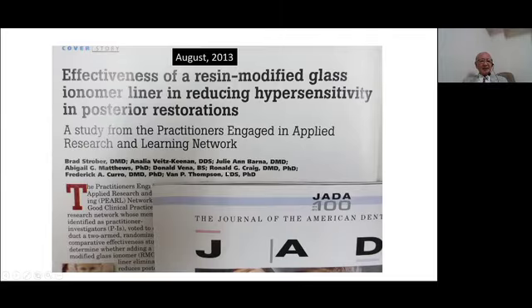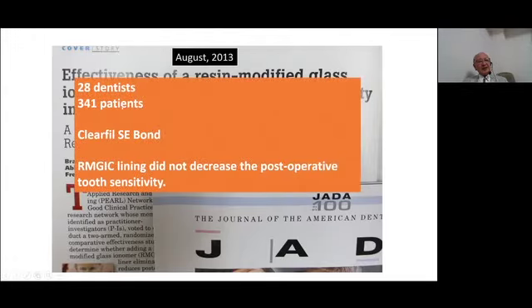Okay, this is a publication in the Journal of the American Dental Association, and in this clinical report, after posterior restorations, the postoperative hypersensitivity was compared between glass ionomer lining and without lining procedures. Twenty-eight clinicians were involved in this clinical survey, and the total number of patients was 341. In this study, Clearfil SE Bond, one of the most reliable adhesive resin materials, consisting of a self-etching primer and a light-cure bonding resin, was used.